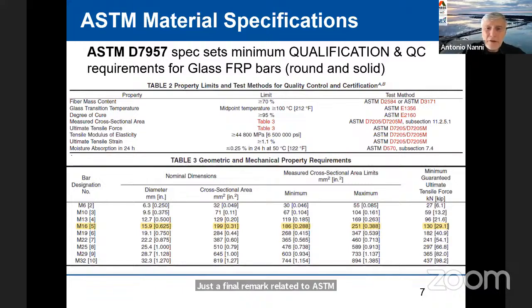Just a final remark related to ASTM. The committee D30.10 that is responsible for this spec has just recently published another one, D8505, that I'm not going to cover today, but the peculiarity of that one, in particular, as far as we are concerned today, is it specifies the characteristics of bars with the modulus of elasticity of 60 GPa, as opposed to the ones that you see listed here that are limited to 45 GPa.